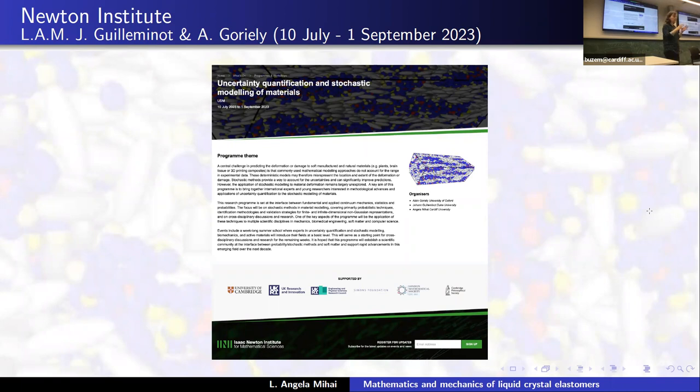But what was observed is that people are becoming less and less confident in using just the neoclassical form based strictly on the Neo-Hookean, because some kind of anisotropy has been observed. If you measure the elastic responses perpendicular and parallel to the nematic director, the elastic modulus does not come out the same, even if the nematic director rotates, which it does. In liquid crystal elastomers, it's not like in fiber material that remains fixed. The director rotates with the force, as you saw. But it does not rotate immediately, so for a while it does have this kind of anisotropy. And this is not well captured by the neoclassical, Neo-Hookean type of model.